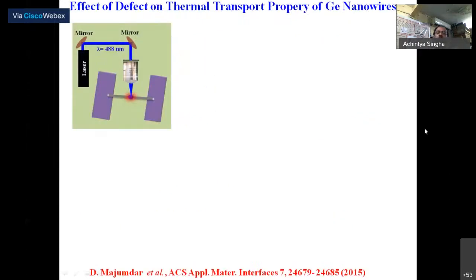So using this behavior, we did a very interesting experiment. You can see in the picture a nanowire which is suspended, like a bridge between two pads. Now if we focus the laser light at the middle, the laser will create some heat, which gives local heating. You can measure how much the temperature has increased from the Raman spectrum, because the Raman spectrum will give you information about the temperature.